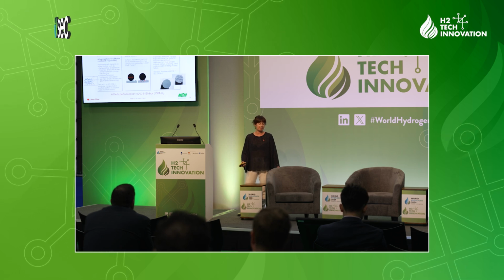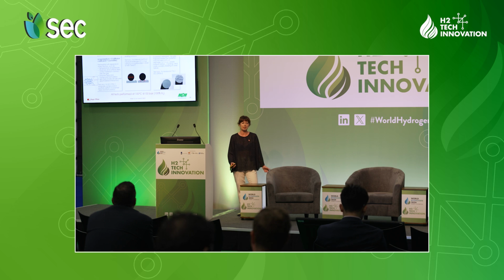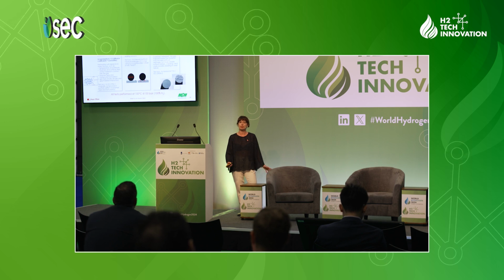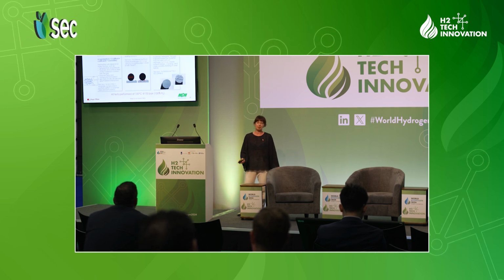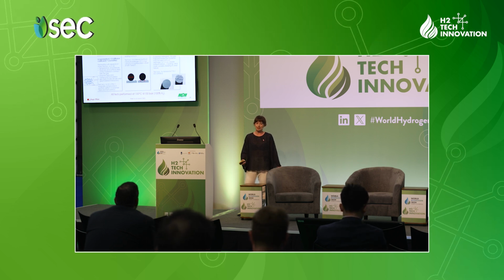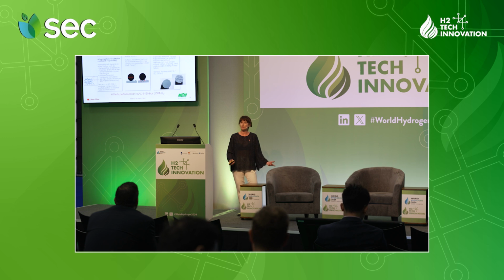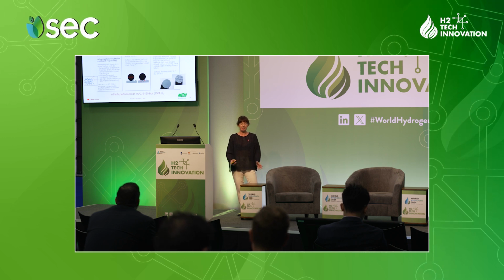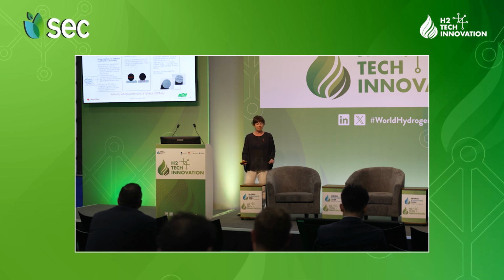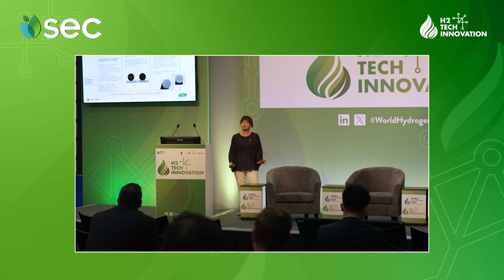Last but not least, on some specific materials, we decided to also run some rapid gas decompression testing according to NORSOK standard M710. Rapid gas decompression is an important issue to be considered when talking about elastomers in contact with gases. Gases at high pressure can permeate into the elastomer, and when the pressure is suddenly released, you can have this gas escaping the material. The gas can escape without any damage, but it can also cause big damage like blisters, voids, and cracks that will then lead to seal failure, basically. So this is the main testing we have started to do, all performed at 100 degrees C, 150 bars in pure hydrogen.